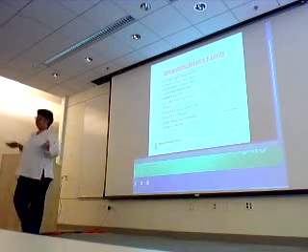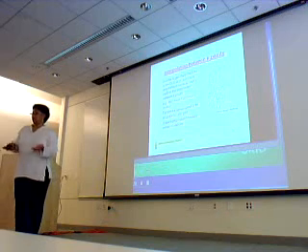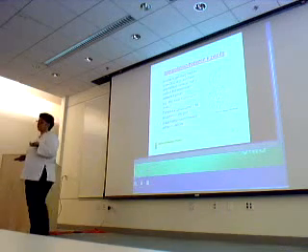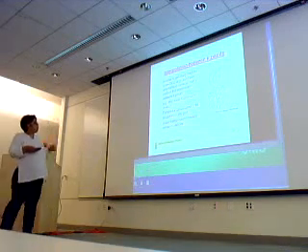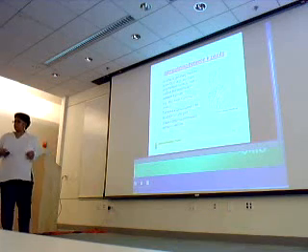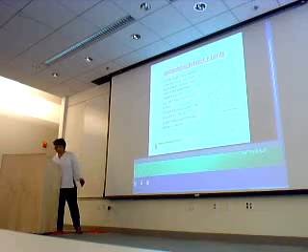And if you want, you could say, well, I want to sample just at a discrete grid, but I want to do some interpolation between these. And there are methods that allow you to do this. For example, in our code, you have the option of doing this with the linear tetrahedron method, where you take a grid of k points and you break up the in-between region into tetrahedra, and then you do an interpolation within these tetrahedra. And this, for example, would be a good thing to do if you want to get fine features like the Van Hove singularities correctly.